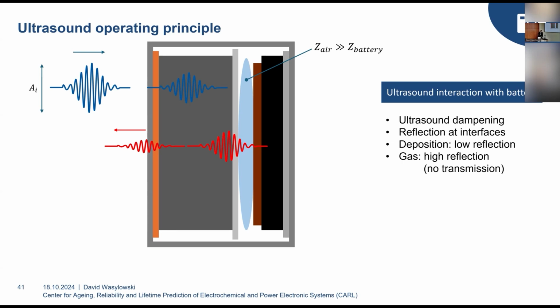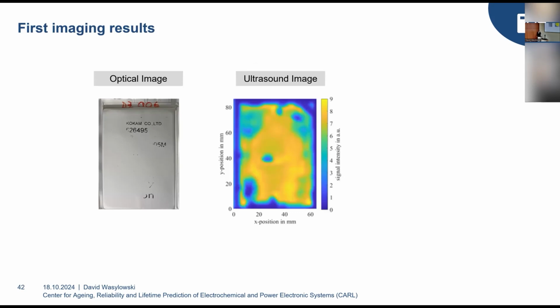So just to sum this up, we have ultrasound dampening in a homogeneous material, and whenever there's a material interface, we have reflection and transmission, and if we have very different materials, the reflection is pretty high. So if we now revisit this ultrasound image from earlier, we can now with more confidence say that this whole yellow plane is probably a fairly homogeneously aged battery with not too severe aging here, and these blue and green islands seem to be a gas accumulation in this blue case because we don't have any signal penetrating the battery, and this green one is probably some deposit or manufacturing defect or a combination of the two.